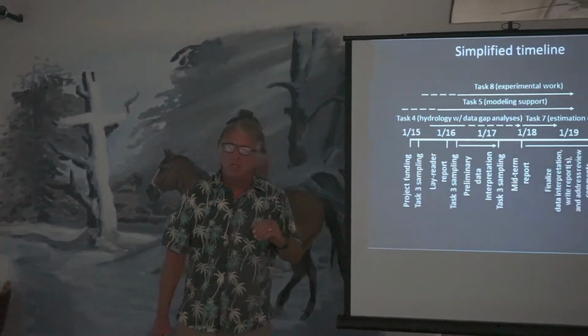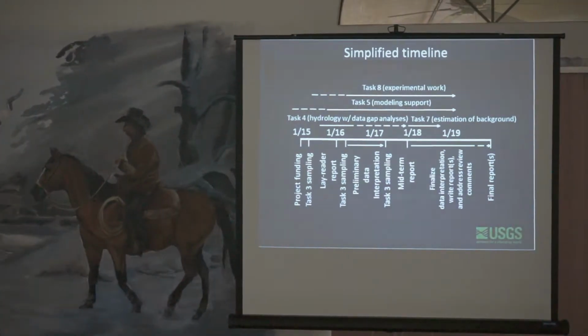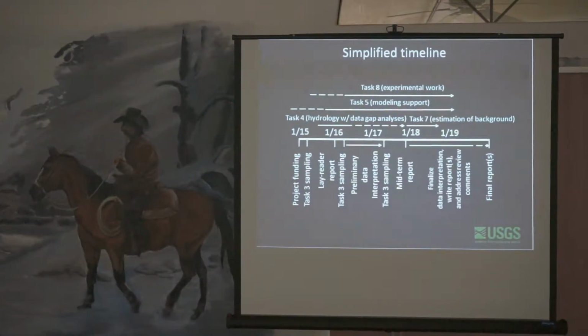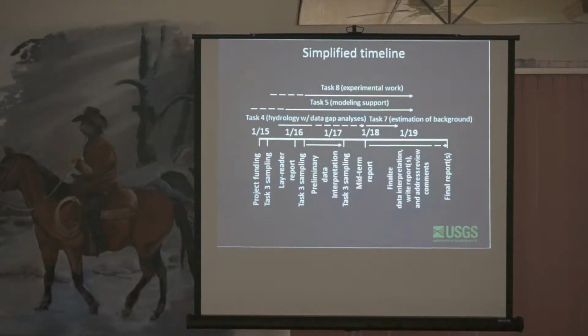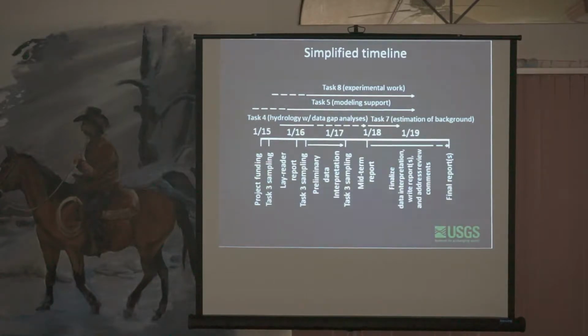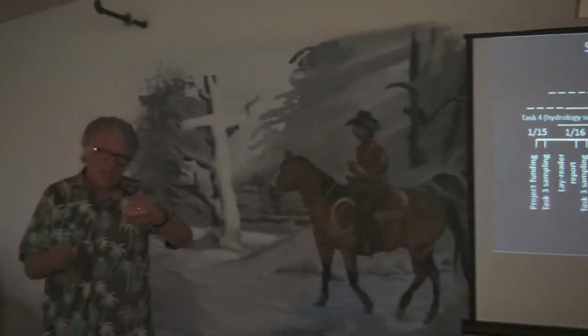Oh, thank you. Yes, task 8 is the experimental work that is being done by my colleagues up in Menlo Park, and we're looking at 2 things there. We're looking at what happens with chromium in the in situ reduction zones within the aquifer, and these are batch experiments, and what we want to know is at the actual mineral grain level, where does the chromium end up when it's reduced? Is it going to be refractory, which means non-reactive, and stay put, or is it likely to be mobilized in the future? And there are 2 experiments there. One looks at how tightly bound it gets with the mineral grains, and the other one looks at how rapidly it can potentially be remobilized if oxic conditions are restored to the aquifer. That's the one that has another 2-year time step to be completed.